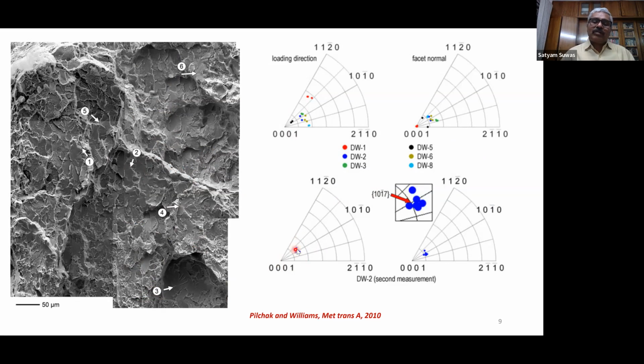So here, particularly in this case, we could see various cases that have been examined, and almost all the orientations of grains where the dwell fatigue cracks have initiated are primarily close to basal orientation. May not be exactly basal orientation, but very close to basal orientation. Like for example, here it was identified to be (1017) orientation, right?